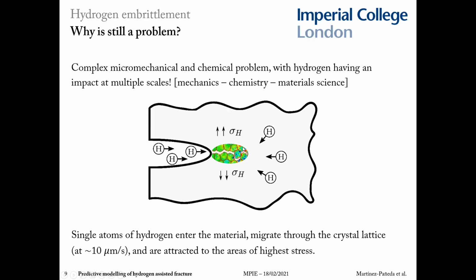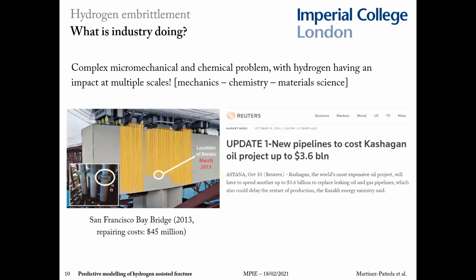So the physical picture is quite complicated. For example, at the atomistic scale, hydrogen can reduce the bonding strength between metal atoms. Hydrogen can also stabilize vacancies. Hydrogen can change the dislocation mobility, and so on. And this lack of scientific understanding comes, of course, at a great cost.